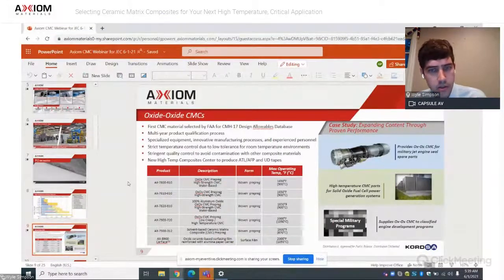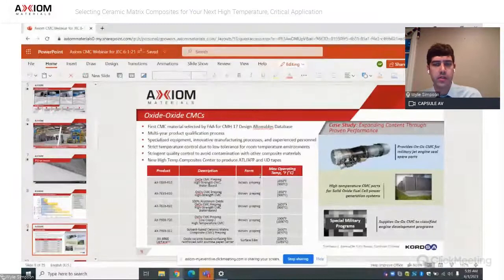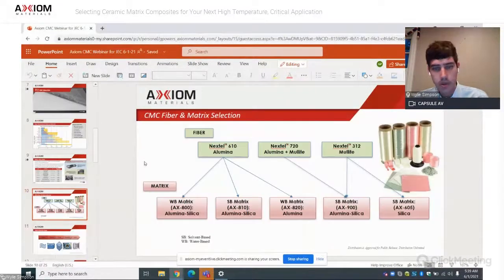Yeah, so here's just a quick list that I'll talk through in more specifics on the next few slides. So there's the 610, the 720, and the 312 fibers offered from 3M, and we have different solutions to matrices to coat them with. The 610 all alumina fiber is the more structural grade component, and this is structural at room temperature. When it goes up to high temperature for long continuous use, the 720 is more preferable due to its creep resistance, and then the 312 is sort of the lower cost grade ceramic, which has a few unique properties to its system that I'll discuss.